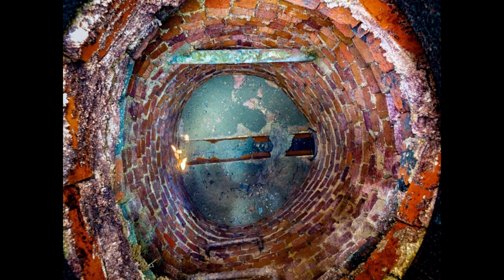If you look at this brick manhole, this picture was actually provided to me by John Vogel. So this is apparently a manhole out in his collection system. As you can see, that's in pretty bad shape. As we talked about earlier, our process is to apply a cementitious underlayment first and then an epoxy coating. The reason is that this structure is so rough and uneven that it would be almost impossible, or very difficult, to apply an epoxy coating by itself and get it continuous and holiday free.